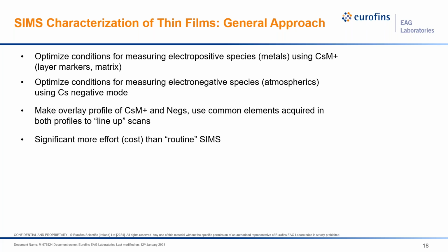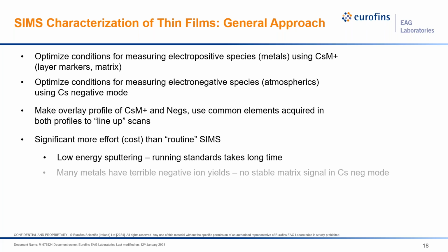Routine SIMS usually, for example, measuring an ion implant in silicon, is a single profile maybe showing one or two elements, or a couple of elements at a time. Obviously, when looking at a variety of elements in different modes, this is more costly. So with lower energy sputtering, many of our standards will take a long time to sputter through, so that also is part of the cost.